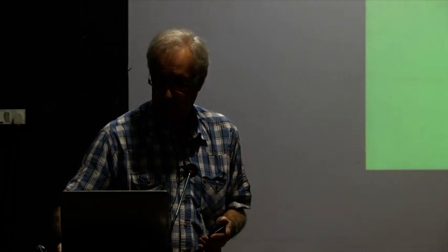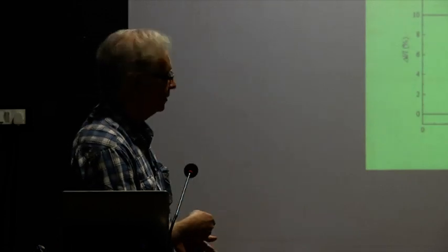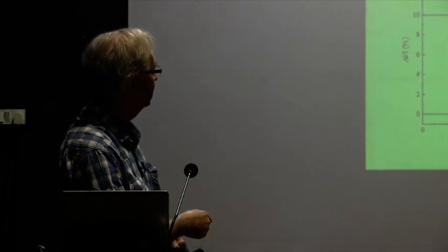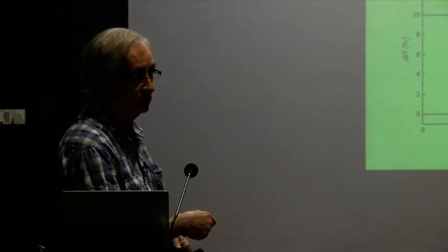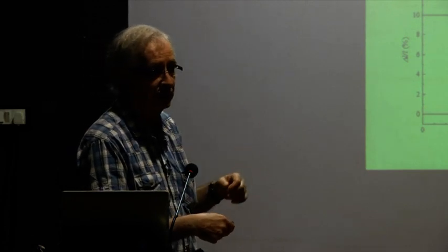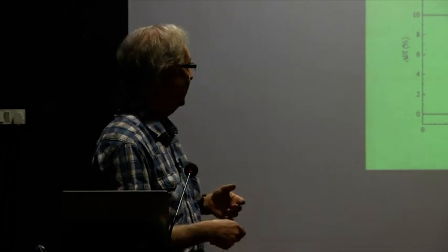And then, okay, this was the stress-strain part of the deal. And here there's a little mistake which I have to fix before I do anything else with that. So we're going from one variant to another variant, a gray variant to a blue variant. And I've shown here that the sample gets shorter. If it gets shorter by delta L, but the change is delta L, and delta L is in the order of about 10% in this case.